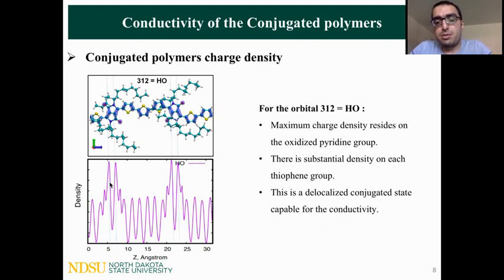But for the HOMO, the maximum charge density resides on the oxidized pyridine group. This is a substantial density. There is a substantial density on each of the groups, and as is clearly visible, this uniform distribution of the charge means that this delocalized conjugated state is capable of conductivity. Next, please.